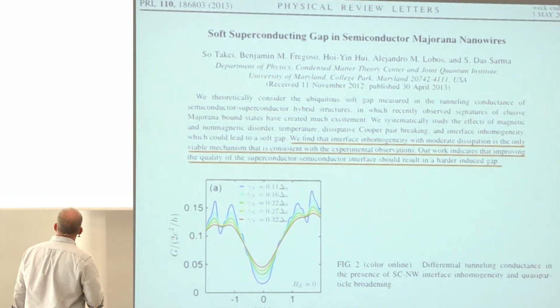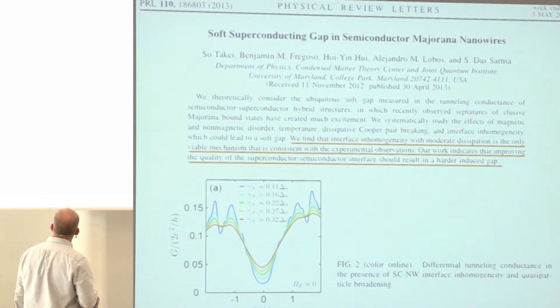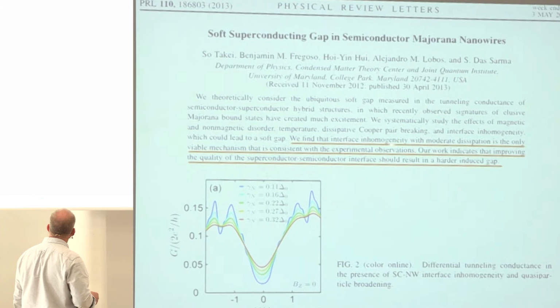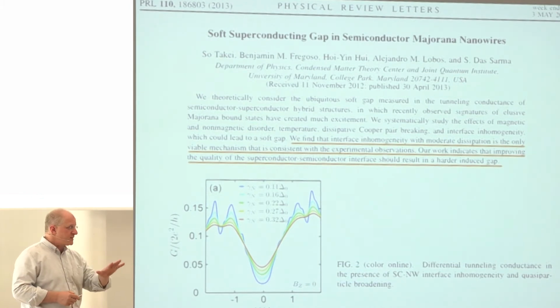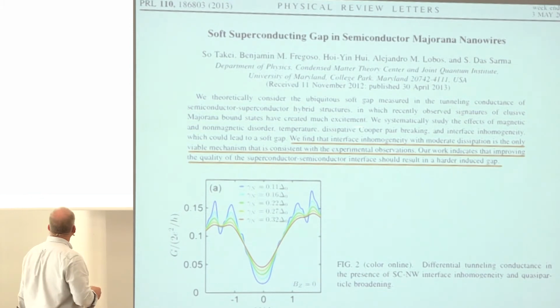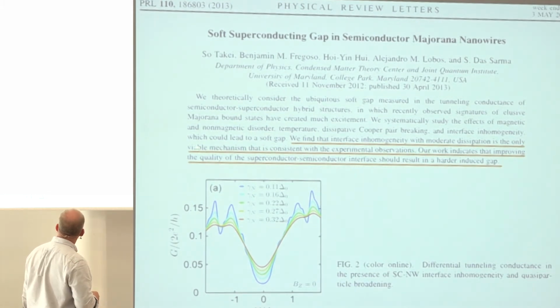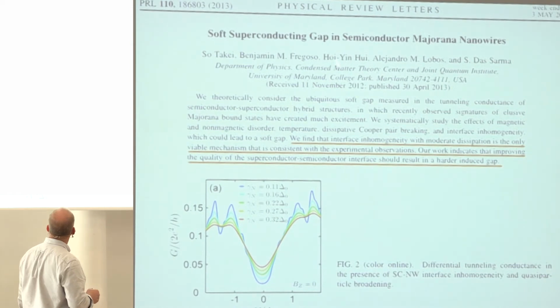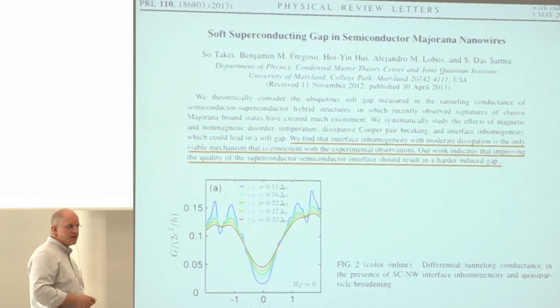So this thing is not only a mystery and a kind of an annoyance, but it's death to topological quantum information. If you read this theoretical paper, I'll just give you this line from the abstract. It says, we find that interface inhomogeneity, the interface between the superconductor that has been put on to proximitize the wire, with moderate dissipation is the only viable mechanism that is consistent with the experimental observations. Okay, that's a pretty strong statement, but you get the point that interface inhomogeneity is responsible for this soft gap, as they call it in the title, in the numerical experiment. The work indicates that improving the quality of the superconductor-semiconductor interface should result in a harder induced gap.